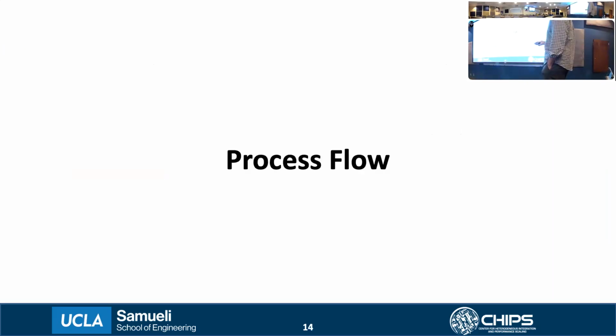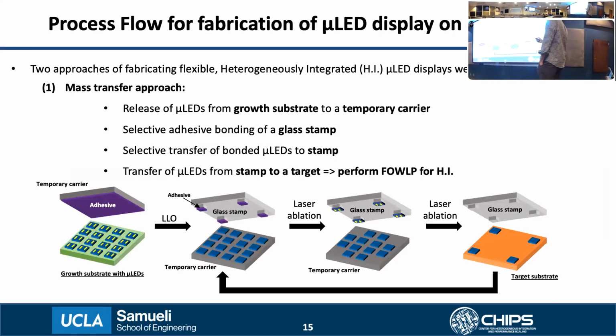Yeah, I'll talk about the process. So now let me talk about the process flow. Essentially, there were two approaches of fabricating these flexible, heterogeneously integrated micro LED displays that we explored. The first one is the so-called mass transfer approach, which essentially involves 4 steps. The first one is the release of the micro LEDs from the growth substrate to a temporary carrier. Then the selective adhesive bonding of a glass stamp, followed by selective transfer of the bonded micro LEDs from the temporary carrier to the stamp. And then finally, transfer of the LEDs from the stamp to the target, followed by performing fan-out wafer level packaging for heterogeneous integration. So this is a schematic of what that would look like.